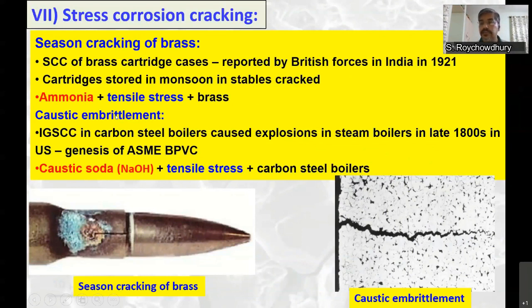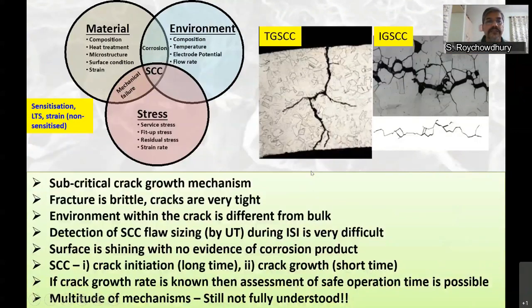Similarly, caustic embrittlement: there were a lot of instances of carbon steel boilers exploding in the United States in the late 1800s. Those accidents were the genesis for the ASME boiler and pressure vessel code. The main reason for this IGSCC, I will explain what IGSCC is, was the presence of caustic soda in the water, tensile stress due to operational stresses, and the material was carbon steel boilers. So you need three factors.